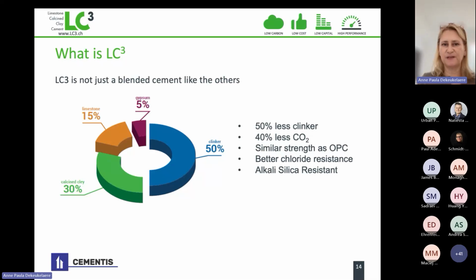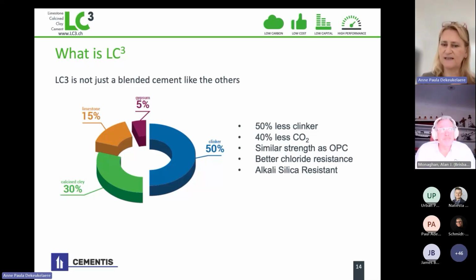Let's come back to the recipe. So as I said, 50% clinker, 30% calcined clay that has to be calcined at 850 degrees C, which means, yes, we need a calciner. I will come back to that. 15% limestone, 5% gypsum. With this, we have 50%, 45%, let's say, less clinker, 40% less CO2. We have the similar strength as the ordinary Portland cement, and we even have better chloride resistance and alkali silica resistance. So it's a product with much lower CO2 and the same properties and even better than the original recipe.